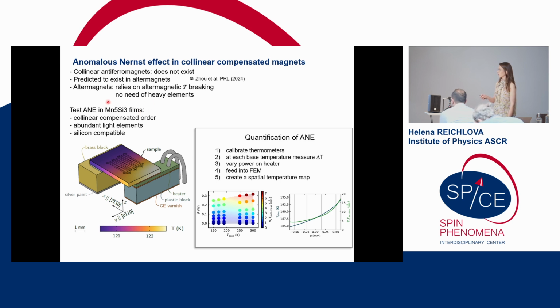So it was natural to think, let's test it in our Mn5Si3 films, because these are some of the lightest, most abundant elements we can have. It's directly on silicon, directly a thin film. So let's try to measure it. This is the experimental setup which we had. We have our thin films, a macroscopic heater on one side and a good heat sink on the other side, so we develop a thermal gradient. This part I will skip, but just to tell you that quantifying the gradient is significantly more work than actually measuring the anomalous Nernst effect.